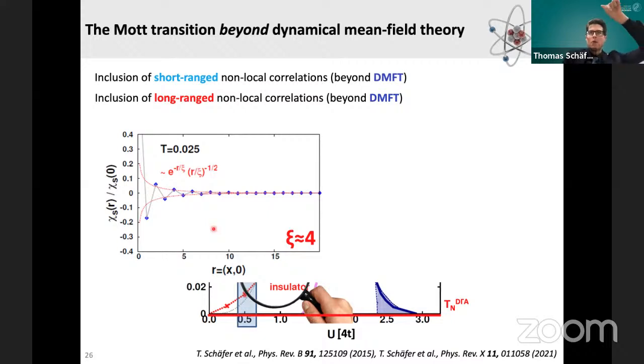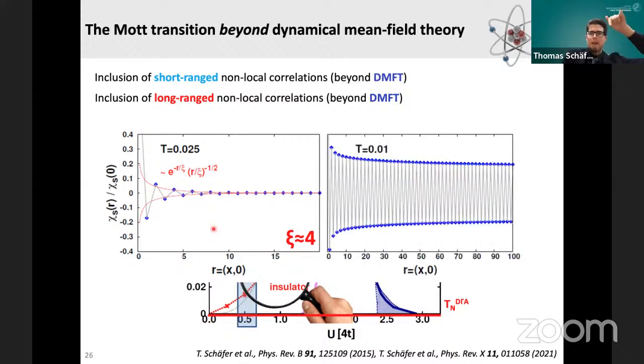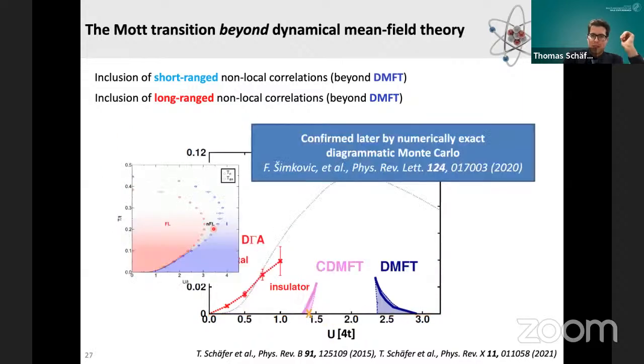On the other hand, if we go lower in temperature, below this crossover line, we see that these fluctuations get quite severe, and the correlation length is about 1,000 lattice sites. And these extended fluctuations are enforcing the electrons to localize. So this is why we get an insulating phase at weak coupling. These D gamma A calculations have been confirmed later on by numerically exact diagrammatic Monte Carlo calculations of Fedor Šimkovic et al.